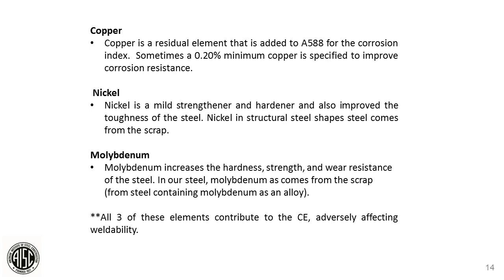Talk about copper. Copper, typically in structural steel, is a negative element. It's a residual element in the steel when we melt the scrap, unless you're talking about 588, where we purposely add copper to improve the corrosion resistance of the steel. Nickel is a mild strengthener and hardener. It also improves the toughness of the steel. Nickel is in structural steel shapes. It usually comes from the scrap. We typically don't add this in structural steel.